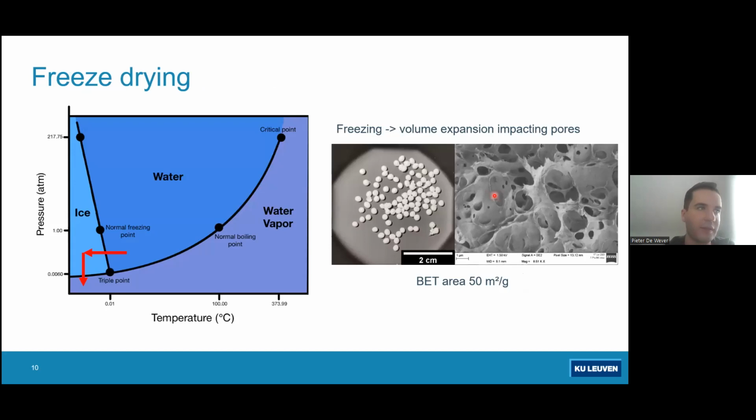So with these cellulose solutions, we prepared cellulose beads. Next, these particles were freeze-dried after the ethanol was replaced with water. Typically in freeze drying, during the freezing step, due to the expansion of water, this leads to the creation of large macropores, while much of the finer features in the gel are disrupted.